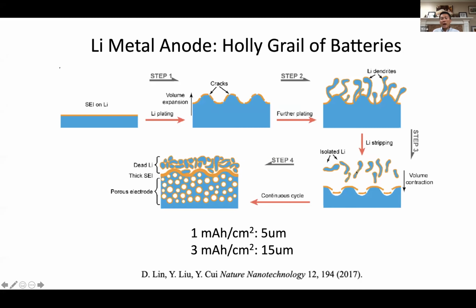That is fine. And when you do the stripping, you also lose control. You can strip, breaking these filamental structures from the bottom or from the middle. You lose lithium metal very fast. You keep forming the solid electrolyte interface because the surface area keeps changing with the electrolyte. So during this process, the volume fluctuation is very big. Every 1 milliamp hour capacity per centimeter square is 5 micron thick of lithium. So the volumetric fluctuation for each layer reaches 15 microns or more because the capacity per unit area you're cycling is really that big.